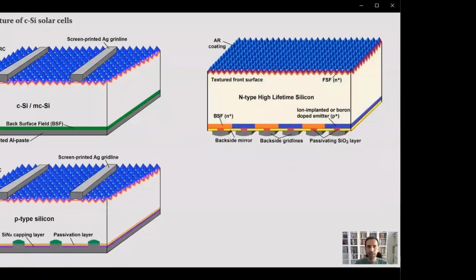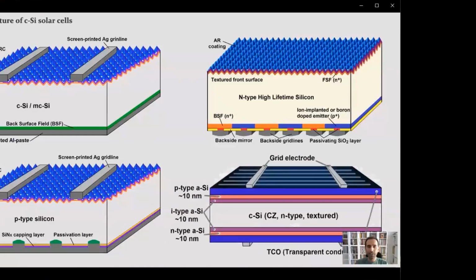Interdigitated back contact is the next one. The fundamental improvement of the design of the IBC cell is zero metal shadowing on the front side, so the current would be maximum. And since the contacts are on the back side, series resistance can be lowered by increasing the width of the back contacts. The last is heterojunction with intrinsic thin layers. The silicon wafer is sandwiched between two intrinsic amorphous silicon thin films to maximize the open circuit voltage. The focus of this presentation will be the PERC type because it is the rising star in the PV market, predicted to surpass the aluminum BSF cell market share in the near future.